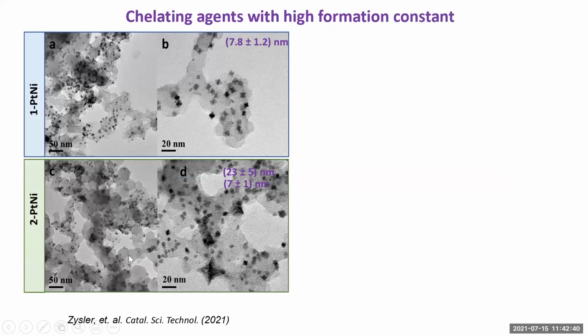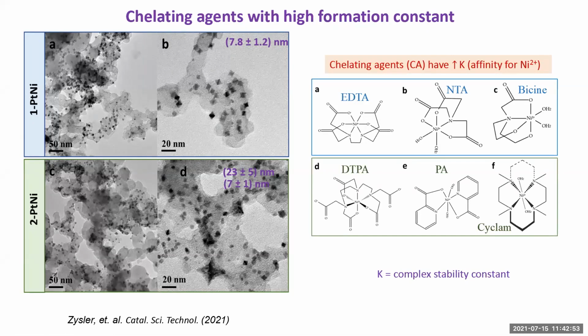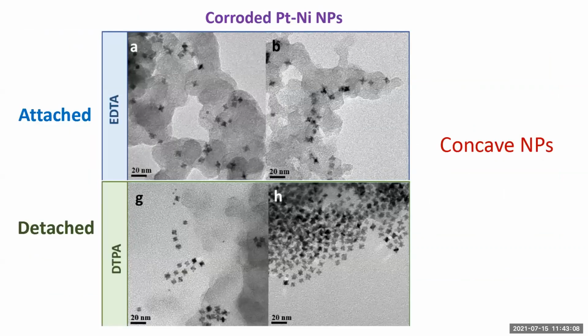So we start with platinum nickel particles, very common, standard size, standard composition, something that is used, and we know the activity. And we expose them to different chelating agents with different affinity for nickel. We try different organic groups, more basic, more acidic, and we tested, as I said, in the two-phase system. What we obtained is that half of the chelating agents keep the particles attached, and half of the other ones detach the particles. And all of them are corroded. All of them were octahedral in the beginning, and they are concave in the end.